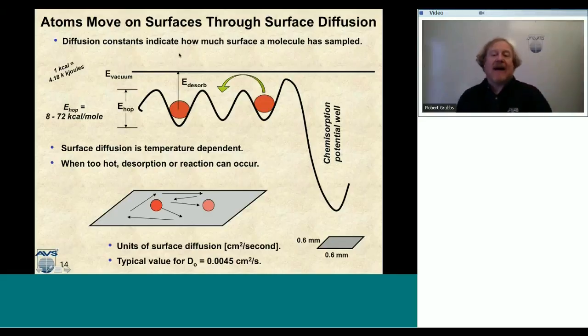And we're going to have this atom actually diffuse along the surface and go up over these humps. It's still going to stay on the surface, but it's going to hop from physisorbed well to physisorbed well to physisorbed well. And possibly it could actually jump over to a higher barrier and make a chemical bond with the surface. And that would be considered a chemisorbed well or a chemical bond with the surface. So what is the energy that it takes to actually hop over one of these little hills to get to the next valley?